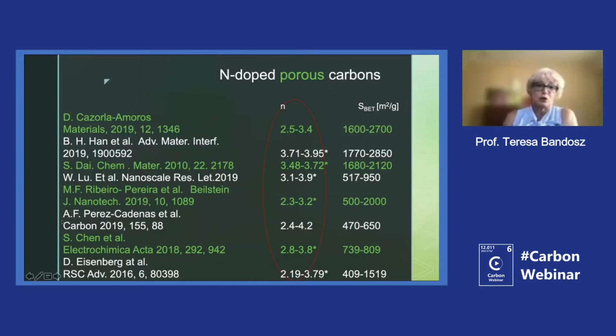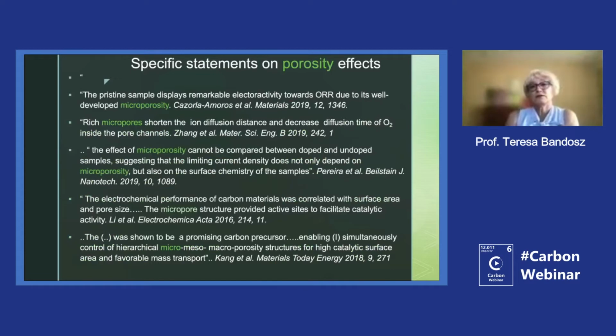and I just show you a few of them, where if we have high surface area carbons, we have a really high number of electrons transferred on them. And there were also some specific statements about the effect of microporosity, either because the carbons which were studied also had micropores, or because there were even no heteroatoms on the surface. So the micropores were pointed out. However, the main stress was on mesopores because they are important for the transport of electrolyte to catalytic centers.